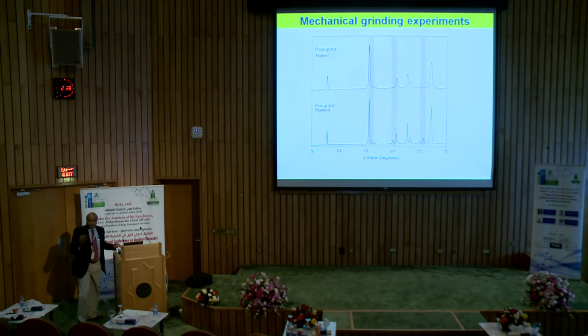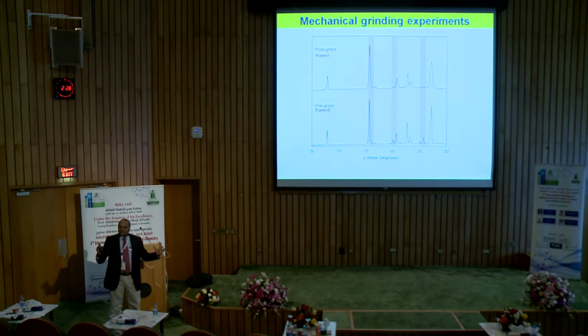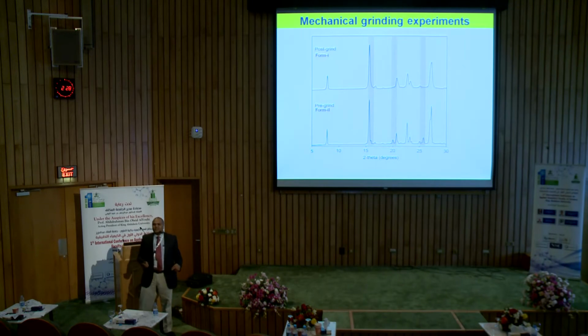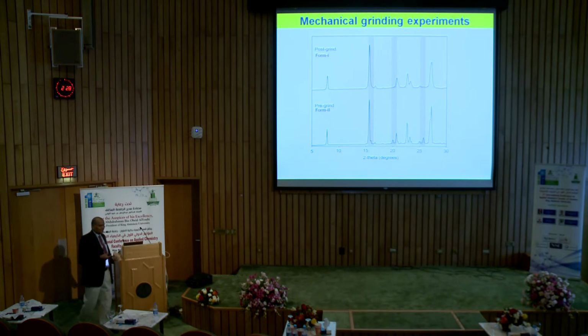Now, you do that kind of mechanical operation. Don't think it's only an academic exercise. In the pharma industry, when they grow these crystals in highly controlled conditions, they afterwards do milling and grinding and tableting. All these are mechanical operations. So if there are possible phase transformations, it could be an issue, and these kinds of studies will tell you this. Now, when we actually initially tried it out, we had all confusing results.